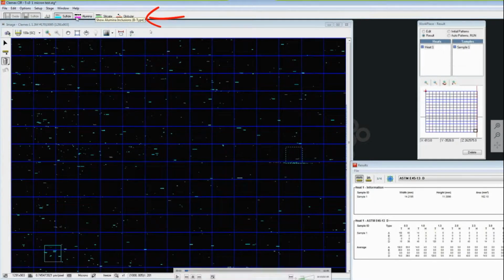So what we're doing now here, we're filtering out the inclusions that we found so that an operator can look at the worst fields for one inclusion. Here, we're only active right now on the sulfide. And what you can see here on the image window became a map of our whole sample. We have a thick square here, which represents the ASTM E45 field of view. And here we have a thin one. So the thick one represents the heavy inclusions, and the thin one represents the thin inclusions.